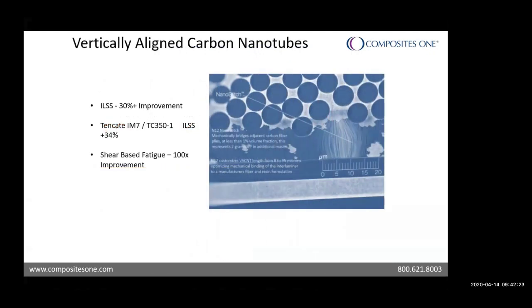So the first one I want to talk about is vertically aligned carbon nanotubes. These are grown on a substrate in a chemical vapor deposition process. They're then placed into a unidirectional prepreg, and the substrate is removed. Now, this graphic representation shows the carbon tubes in cross-sectional view, and then you can see the vertically aligned carbon nanotubes as a forest, if you will, and how they bridge the gap between the ply stacks. So they bridge that matrix, that resin, which is typically a weak link in composites. Typically, if a crack begins to propagate in the resin, it just zips right through the ply stacks, and then you have ply failure.